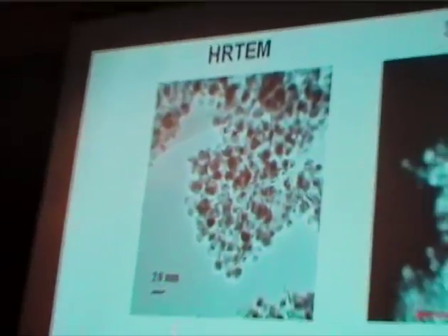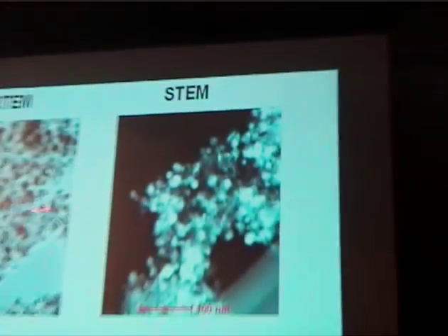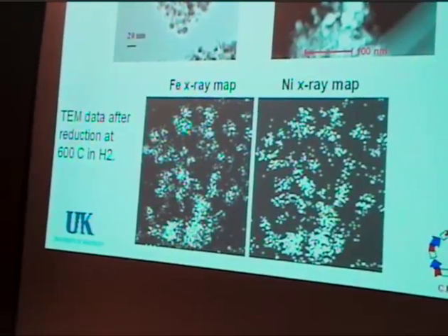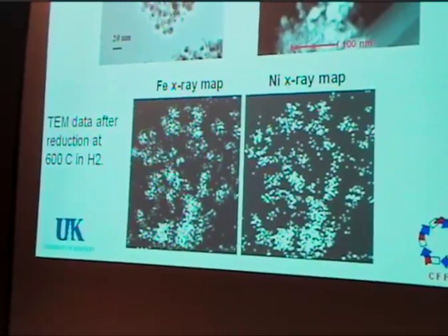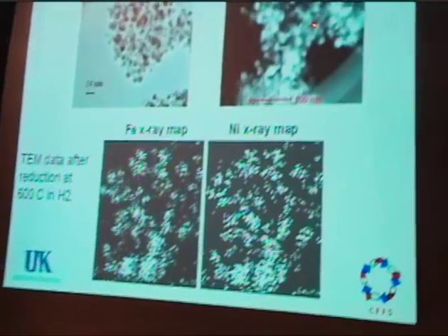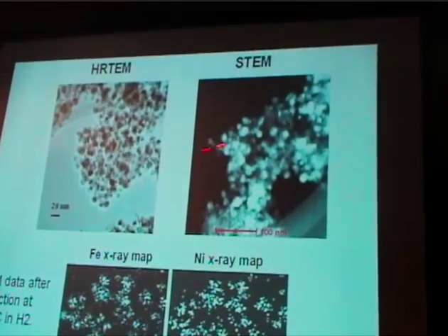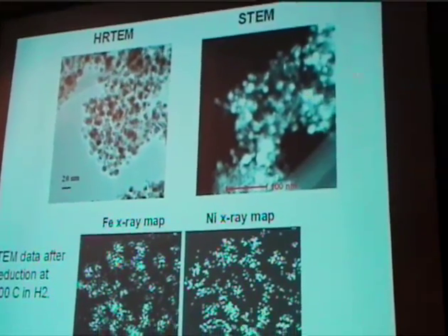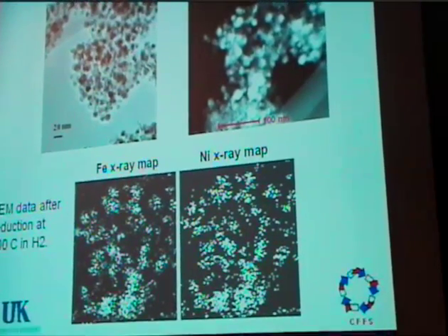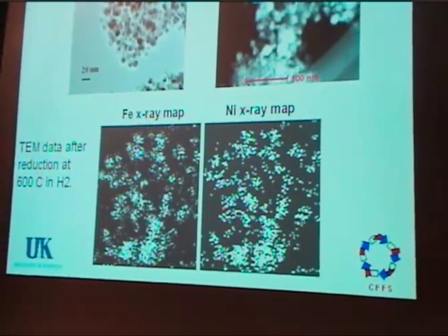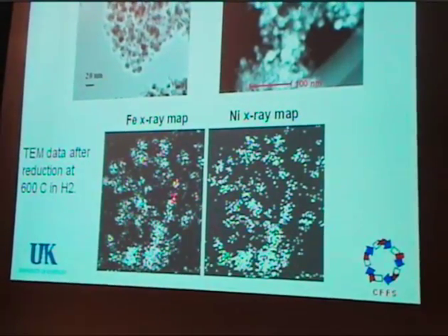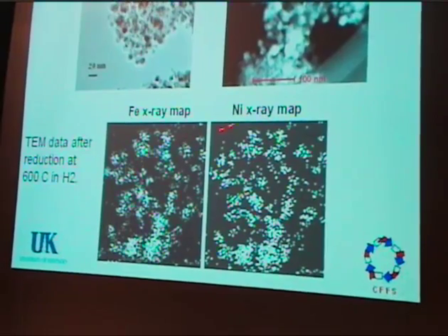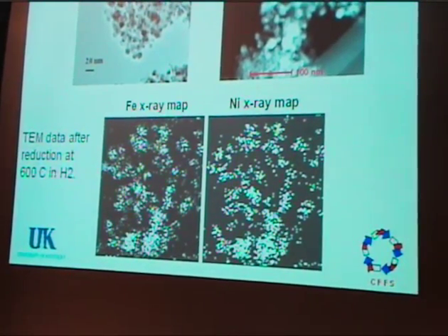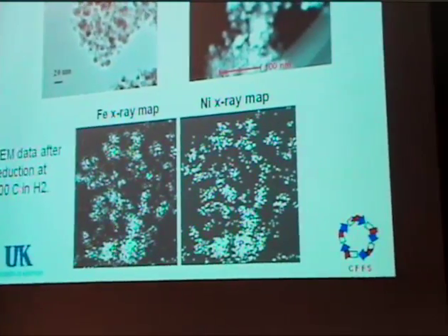Here are some TEM micrographs. The dark spots, of course, are the catalyst particles, and the light gray particles are the magnesia alumina support conglomerate. You can see the catalyst particles stand out a little better in the STEM image. Obviously, we don't have all single particles. We've got some conglomerates of particles that are larger. But we also look at the X-ray maps, and we can see very clearly that we are getting excellent mixing of the iron and the nickel. This is after reduction at 600 degrees C in hydrogen.